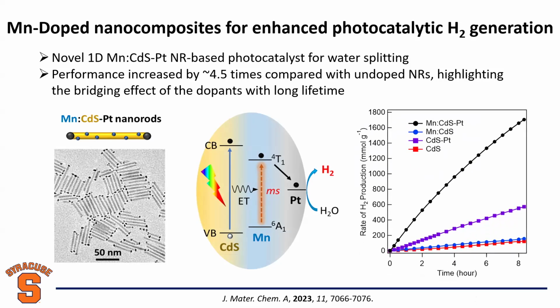All right. So here's the data. If you don't do anything, starting with the cadmium sulfide, no dopant, no platinum, yeah, you can generate hydrogen gas. People have reported this. If you don't add dopant but add platinum nanoparticles, yeah, better. Platinum is a very good catalyst. We knew it. But after we add the intermediate step and generate much more stable carriers, boom, we increase the efficiency by about 4.5 times.